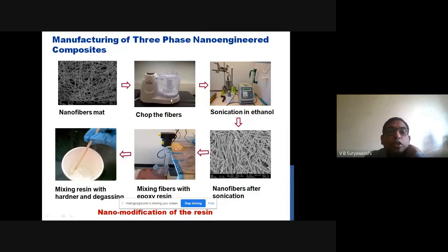So we can chop these nanofibers with the help of some kind of a chopper. We can do the solution mixing. There is a liquid there to sonicate the fibers. Let us say ethanol is used here. It is called the sonication process. After chopping, we can get some fibers like this. Then we mix with the polymer, let us say epoxy resin, and finally we get a modified resin. So this is called the nano engineered resin. So we have mixed the nanofibers with the resin.